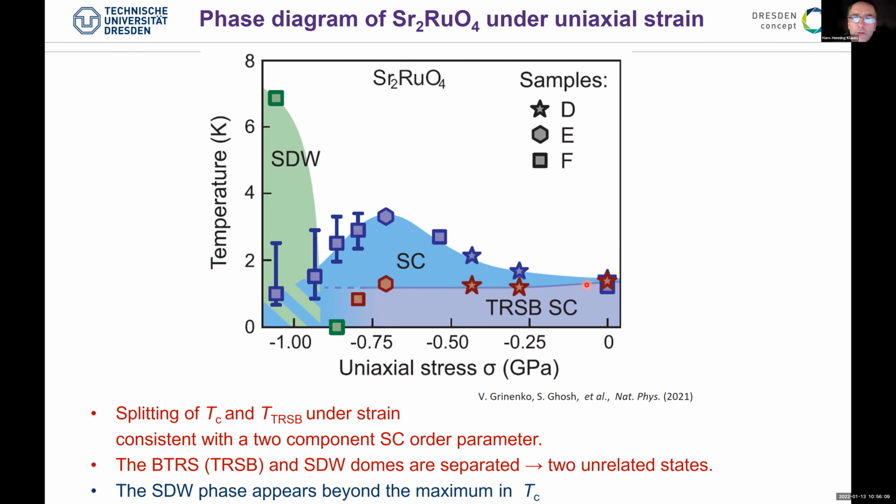The fact that it goes down so weakly, or even not at all, is consistent with the fact that the specific heat at this transition is very weak. In principle, if you think there are two order parameter components, one coming up at a higher temperature and one at a lower temperature, both would give specific heat.